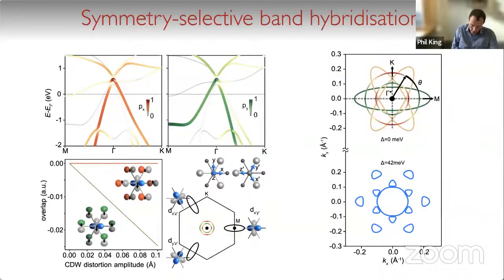And when you look at that, you find that the PY derived valence band states can couple with, if we look, for example, for this pocket backfolded to the gamma point, the D X prime Y prime states, where the prime is the octahedral coordinate system and the non-primed is the crystal coordinate system. So these can couple when you displace the atoms according to the periodic lattice distortion that you have in the system, whereas the PX derived states can't couple. There's then a combination of a mirror symmetry and a C2 rotation symmetry that prevents that coupling. And so it's really between the D and the P states, but the character of the P states is then dictating which of the band crossings are allowed to hybridize and which aren't.